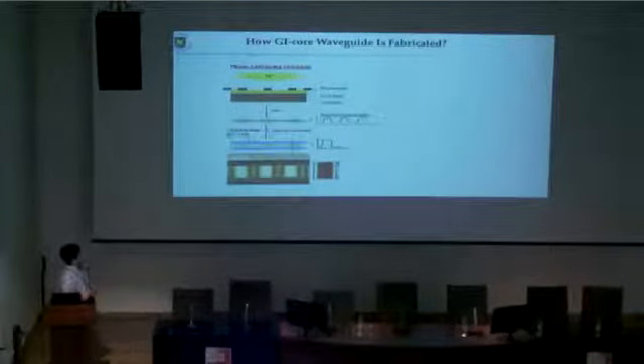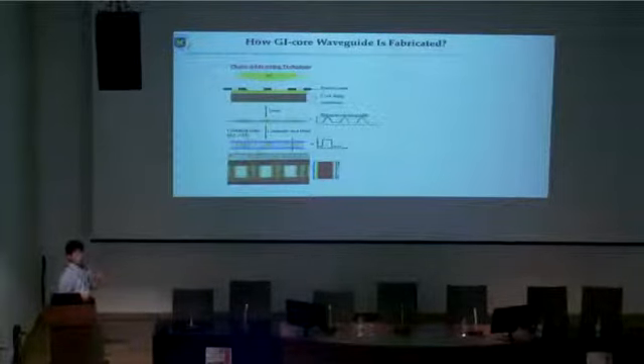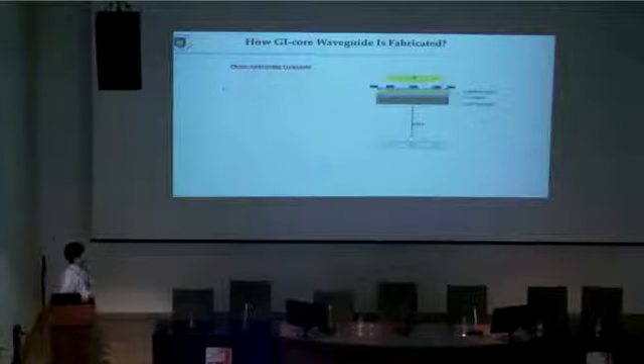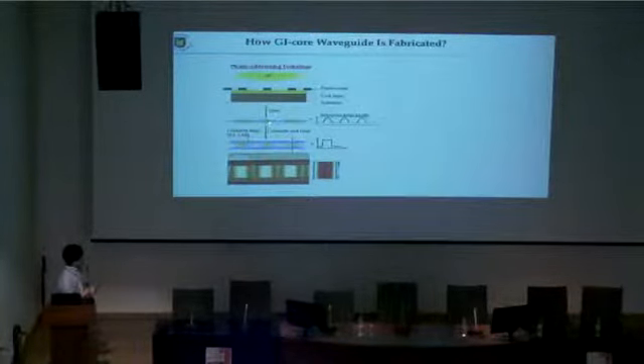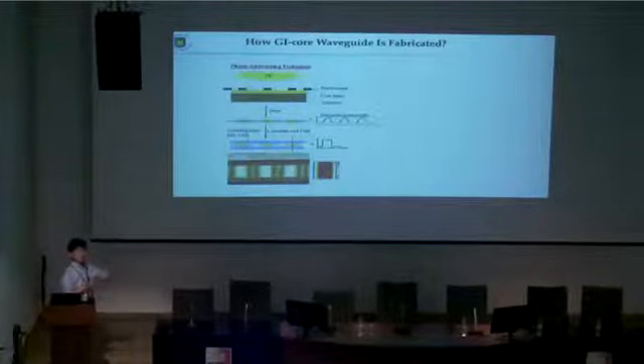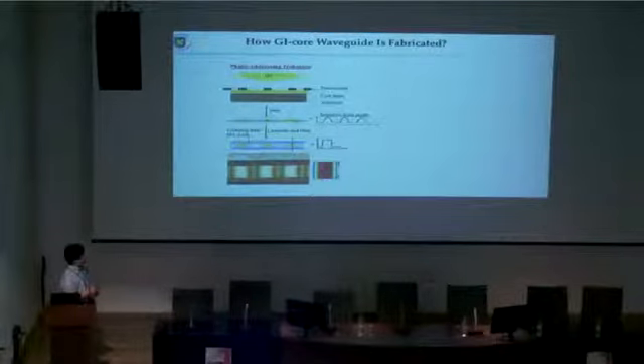Okay, here is the schema of the photo addressing method. Richard Pittman already mentioned it yesterday, just using a photomask. Through the photomask, UV exposure is applied to the core monomer film. In the area that UV illuminates, the curing reaction occurs, while in the shaded area, no chemical reaction occurs. Then the monomers in the shaded area gradually diffuse into the illuminated area due to the volume contraction. Then a concentration distribution in the horizontal direction is formed.